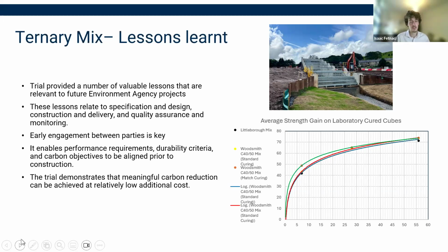And so this trial demonstrated that a meaningful carbon reduction can be achieved at a relatively low additional cost from the concrete, and that additional cost was covered by the DTA program as part of our works. But the plan is that in future the cost of ternary mixes and other low carbon concretes will come down as they become more widespread and more widely available. And hopefully eventually they will actually become cheaper than standard CEM I concrete because they often use waste products and byproducts of other processes.